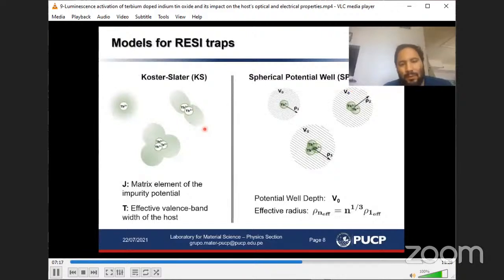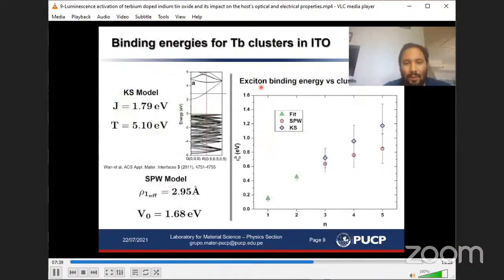So there are two models to treat these rare earth structure isovalent traps. One is the Koster-Slater model, and the other is the spherical potential well model. We have used these two models and the activation energies we obtained earlier to calculate and predict other activation energies or binding energies, assuming that these activation energies are actually the binding energies of these excitons to these isovalent traps.